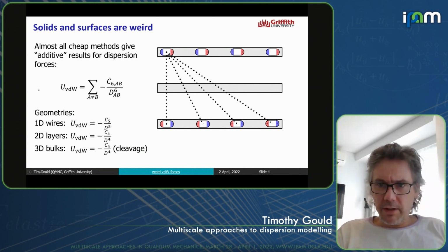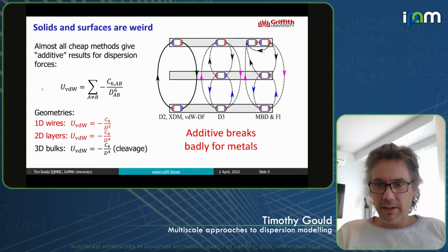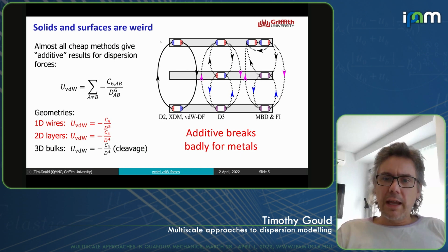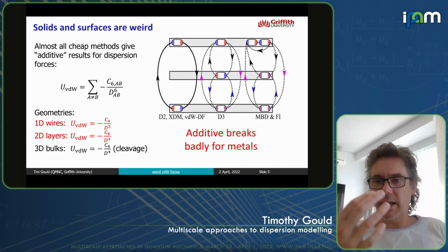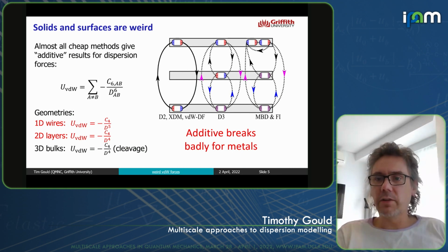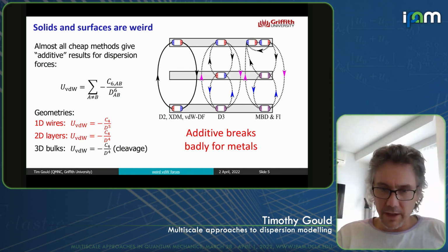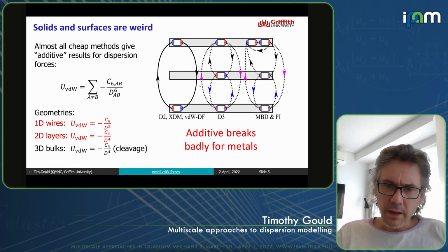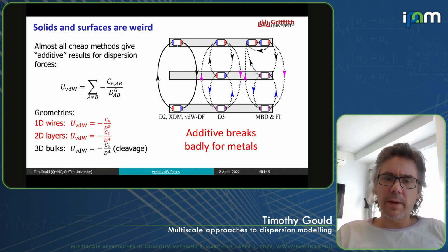But what these additive theories miss is the fact that we don't just have 2 atoms in our system, we have multiple atoms. And each of these atoms, of course, is setting up an electric field from its spontaneous dipoles, which is affecting another atom, which is affecting another atom, which is affecting yet another atom. So, for example, our pairwise terms, basically, we've got our field, as I described before, feeding back 1 on d6.